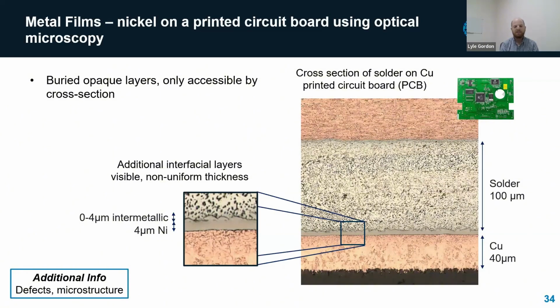So here, if we had just one of these layers, maybe that thin layer of nickel on copper, we could have approached this with X-ray fluorescence. But this becomes a challenge where we have a number of layers that are buried, and they're becoming very thick and have lots of heavy elements. And so here is a nice case where we can simply cut it in half, polish this cross section and look inside and directly measure the thickness.